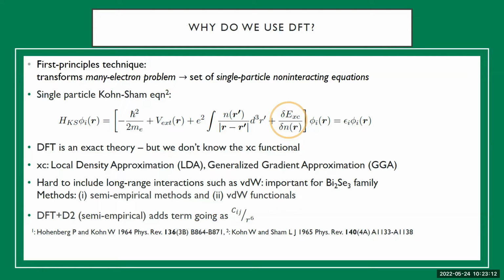So in density functional theory, there are 2 main ways to include the van der Waals interactions. These consist of something called the semi-empirical methods and the van der Waals functionals. So in the first class of methods, DFT adds an energy correction to the total energy, which goes as 1/r⁶, corrected by some coefficient Cij for every pair of atoms, i and j, in the system. And the van der Waals functionals, on the other hand, actually modify the exchange correlation functional to include the van der Waals interactions. One of the important ones is what's called the DFT-D2 technique.